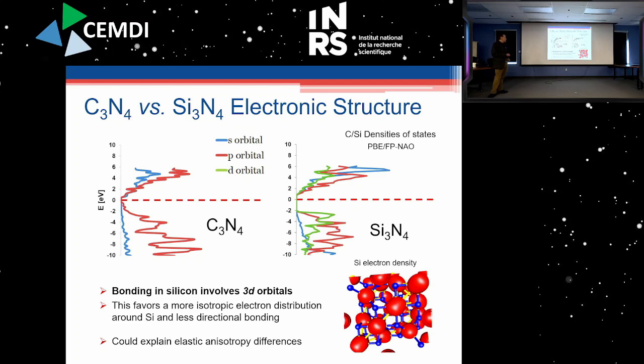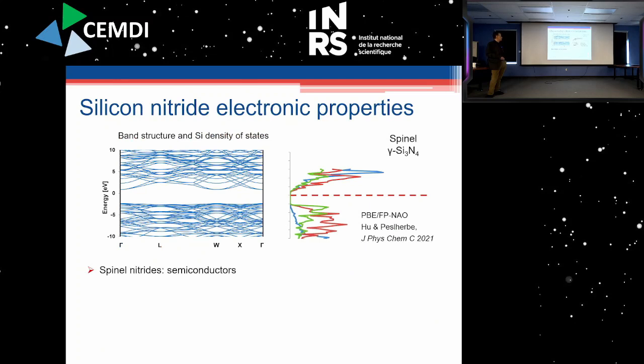And so the fact that we have a population of 3d orbitals, which have a more spherical distribution around the atoms, favors the more isotropic electron distribution in the material and much less directional bonding than what you could expect from the overlap of p orbitals. And so this could explain it, and if you look at the density here, you see that the electron density around the silicon atoms, and the same holds for nitrogen actually, are more or less spherical, which might explain the anisotropic differences. Okay, so we believe that's where this may come from.